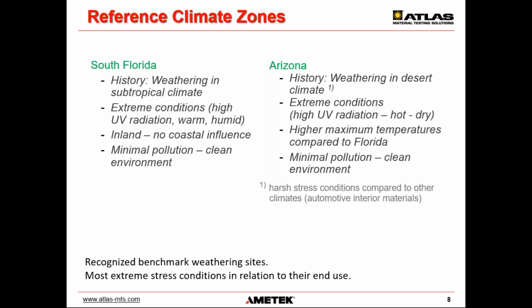So on the left-hand side here, we see South Florida. It's basically just the very southern tip of Florida, which historically has been used for weathering testing in this subtropical environment. We have the extremes that I discussed, such as high UV radiation content through the year, very warm, and also very humid. Not just humid, but it also provides a lot of wet time. In other words, condensation: the amount of time that samples physically have water on them is very high in South Florida, because during the evening, as things cool down, it's very humid. Condensation forms on samples nearly every night.